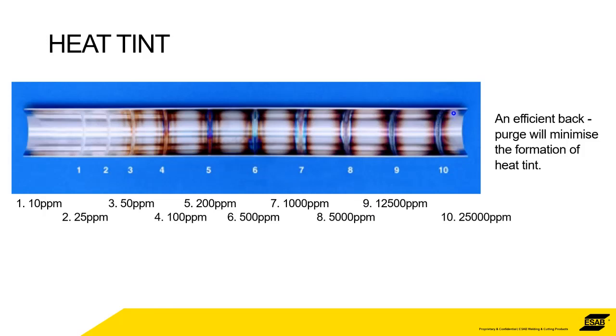What you need to know is just because you haven't got a heat tint, like in number 1, doesn't mean you haven't got a chrome depleted layer. The heat has still gone into the stainless steel, and it's caused the chrome to move. Basically, it's caused the chrome to migrate to the surface. So you still have a chromium depleted layer. You just can't see it. Okay.